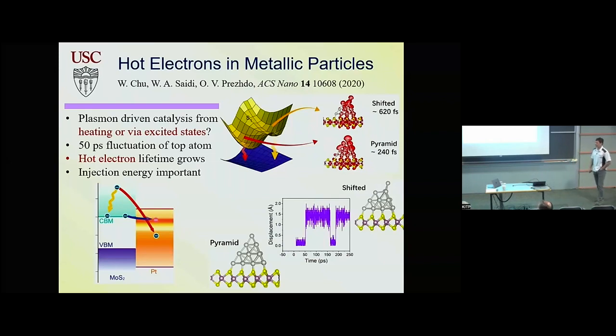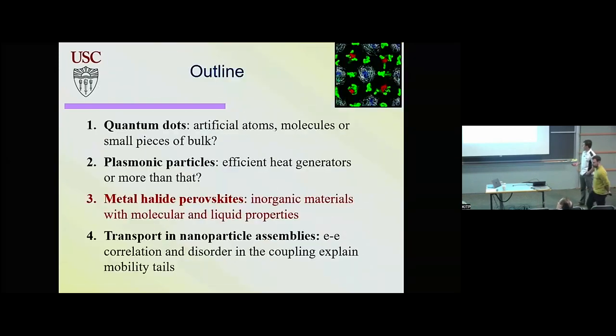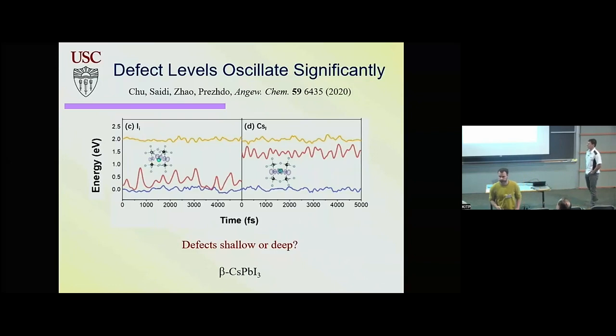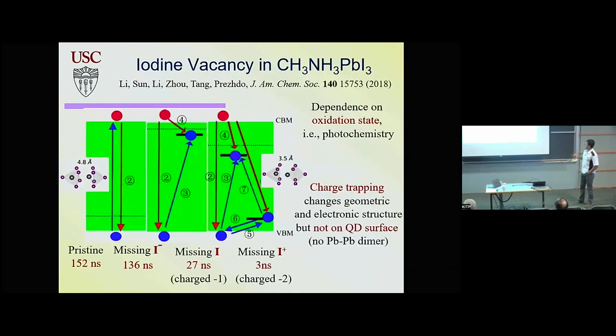I want to follow on this maybe. You've shown that these perovskites, we know, are quite soft. They give rise to these huge fluctuations, and they also have trap states that can go into the gap. How come they do so well in various light harvesting and transport applications? What's your take on this? Yeah, so I think trapping is transient. You can get charges that are trapped, but at the same time, they can be detrapped pretty fast because of thermal fluctuations. You have thermally activated detrapping. That's important. Also, I should mention that, for example, this dimer defect here cannot happen on the surface, because you need two leads between which you're missing iodine, but on the surface you only have one lead.